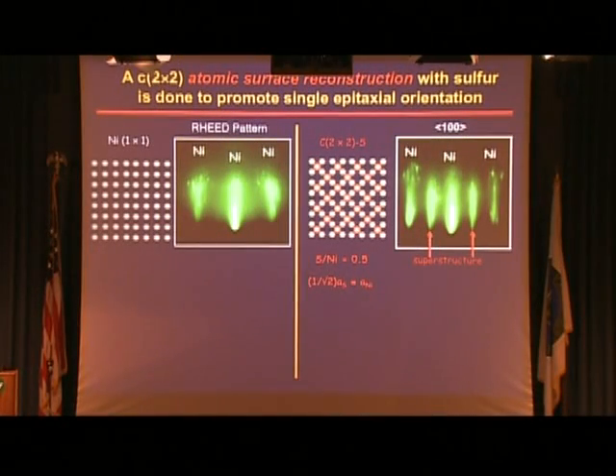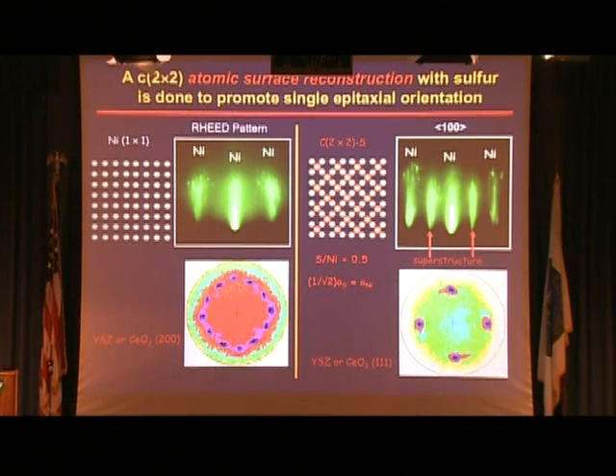Now, we have this aluminum foil. It's really a nickel-based foil, aluminum foil-like material. If you were to look at the atoms on that, you get these white atoms all arranged in a cubic lattice. But what we really want to do is put a sulfur atom in every other unit cell to do a little atomic reconstruction of the surface. We do that only for one reason, because remember, we want to put the next layer down so that it has the same atomic configuration as the metal substrate below. And by putting a sulfur atom on every other unit cell, we get only one orientation, one heteroepitaxial orientation. If you don't do that, we get multiple orientations. So this is one step that we do after we make the foil.